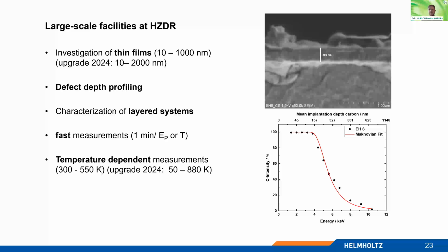And as I said, here is an example for this kind of measurement. In the upper picture, you see a carbon film on top of a porous glass, and in the lower part, there's a graph showing the carbon intensity we get from the positron annihilation lifetime spectrum, referring to the carbon, and this decreases over the implantation energy. So as you see, you can see what happens from the top to the substrate and investigate even thin films. Here, for example, a 280 nanometer film of carbon, which is just an example.